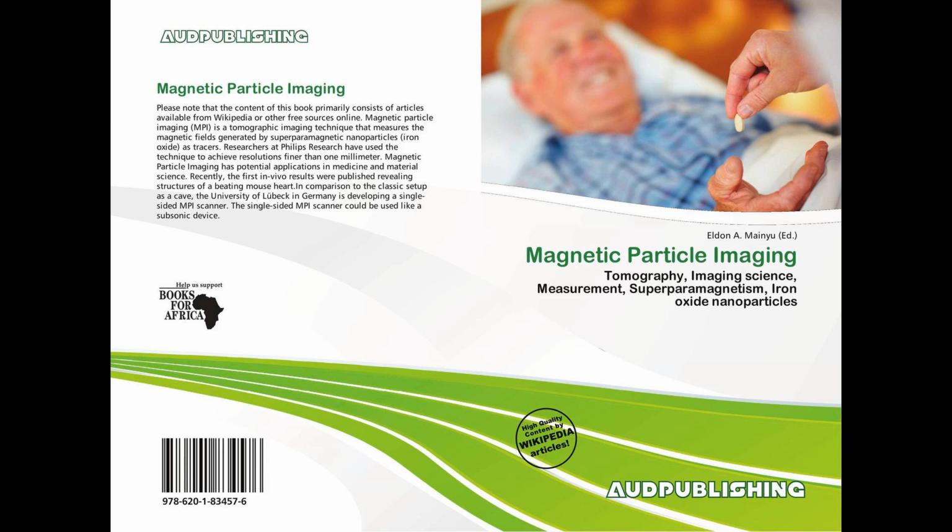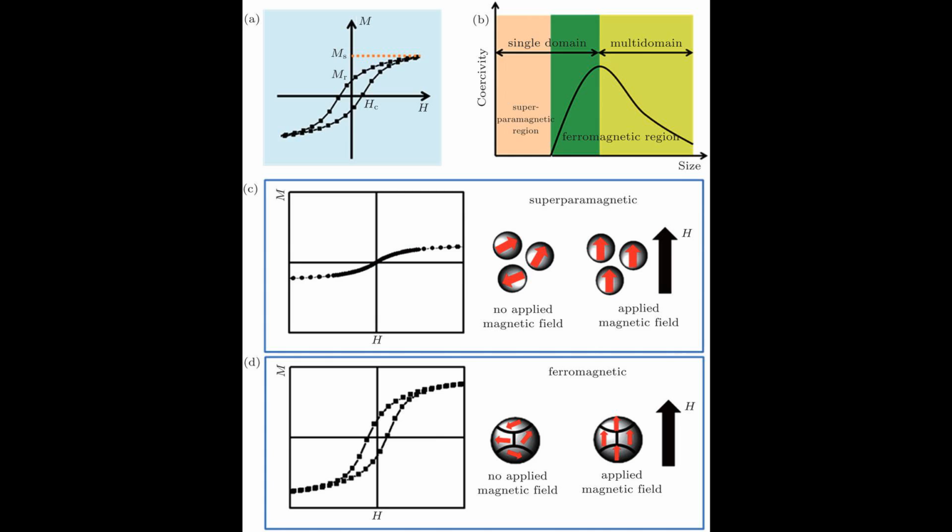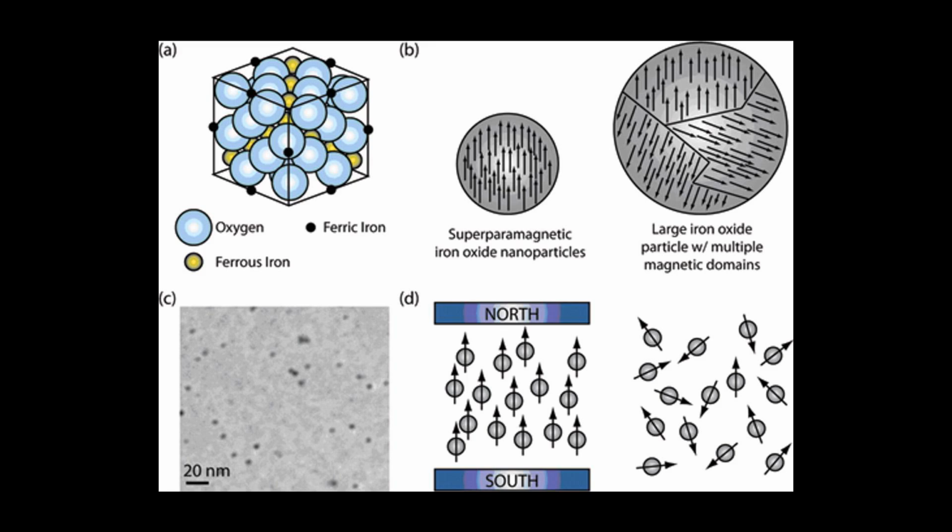Superparamagnetism occurs in nanoparticles which are single domain, i.e., composed of a single magnetic domain. This is possible when their diameter is below 3 to 50 nanometers, depending on the materials. In this condition, it is considered that the magnetization of the nanoparticles is a single giant magnetic moment, the sum of all the individual magnetic moments carried by the atoms of the nanoparticle. Those in the field of superparamagnetism call this the macro-spin approximation.